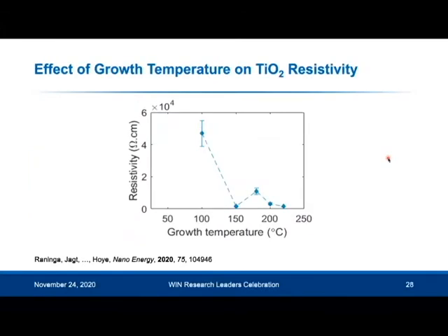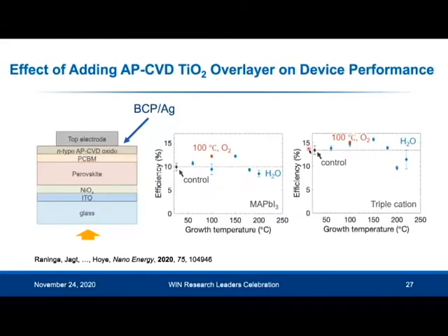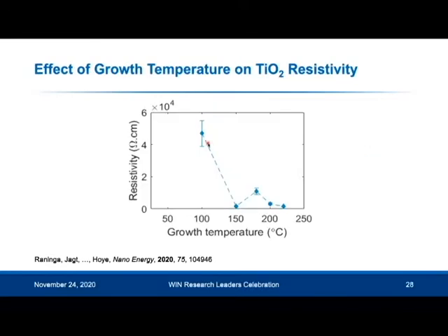And the question is, why is there improvement in the efficiency as we increase the deposition temperature for the oxide? And we measured the resistivity of the oxide, and as we expected, as we grew at higher temperatures, the resistivity became lower. So the oxide buffer layer makes a smaller contribution to the total series resistance of the device itself.